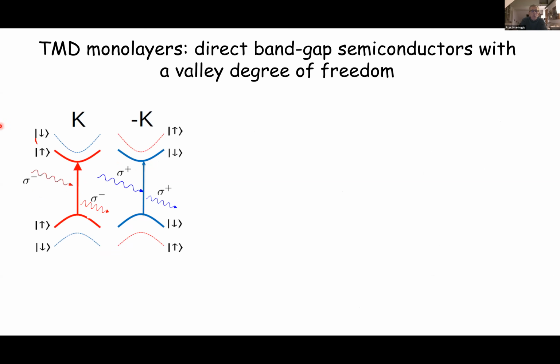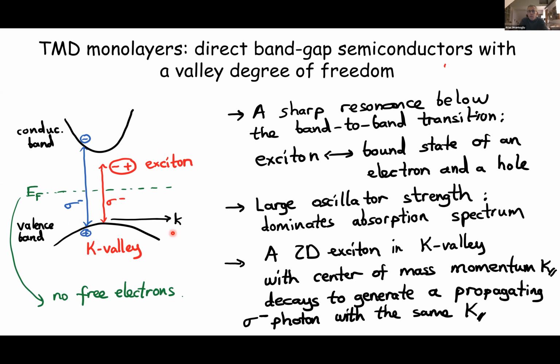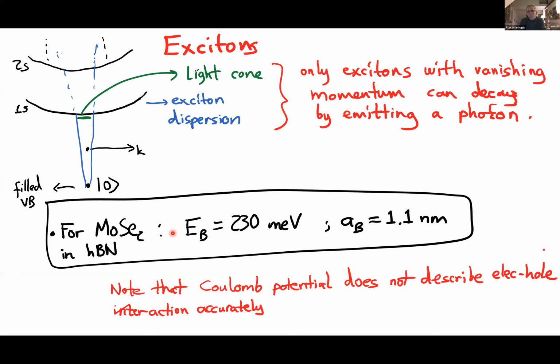So in principle, even though an inter-valley exciton cannot decay directly, it can emit a zone edge phonon and then decay, particularly in that case, where the spin between the lowest conduction band and the highest valence band is the same. That's for tungsten diselenide. For moly diselenide, they do not play a significant role. At least they might be influencing the photoluminescence efficiency, but in the absorption measurements that I will show you, they do not play a role.